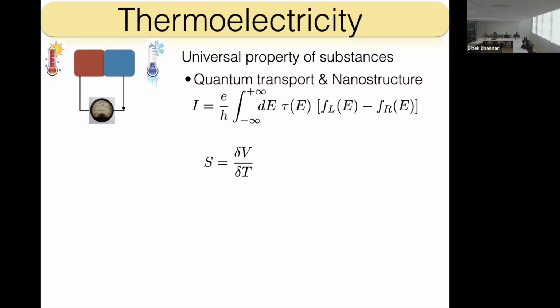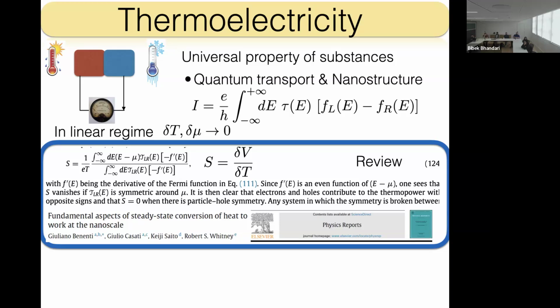And so you can compute using quantum transport because we will consider some coherent system, let's say. And you can define the figure of merit that typically is the Seebeck coefficient. That is nothing more than the voltage difference that you generate in your system due to the gradient of the temperature. This is essentially this basic quantity, it's a linear quantity. And you can compute it using this formula, and you realize that it is given by this formula essentially, where it is important to note that, due to the fact that the numerator depends on the derivative of the Fermi function, and there is also an energy here, this becomes odd.